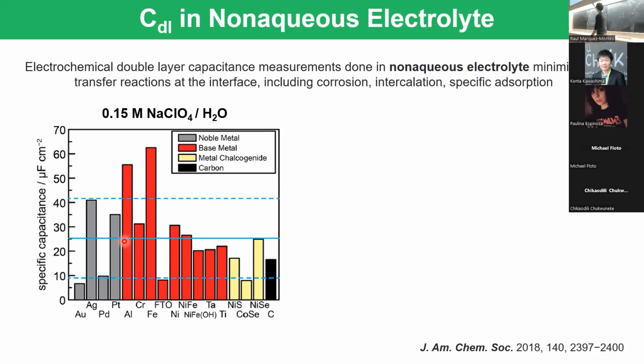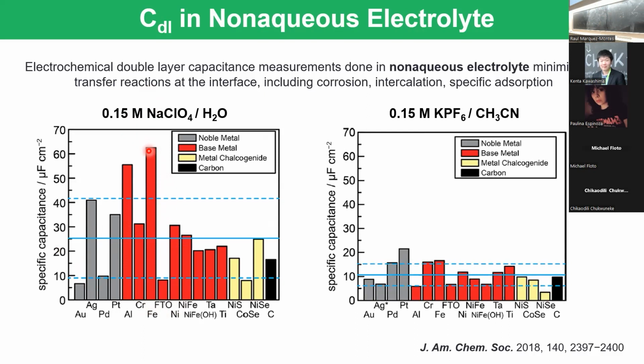But that's wrong, because notice that this average value is not close to, for instance, the values from, was that iron, right? So it's deviating a lot. So that's wrong. But what happens when you use organic electrolyte? When you use organic electrolyte, you can prevent these side reactions from deviating your estimation of the double layer capacitance. And now notice that this average is 11. So this value of 11 microfarads, by the way, farads are the unit of capacitance, is closer to all these materials here. So now you can use this average value instead of 30 or 25, only if you use an aprotic electrolyte.